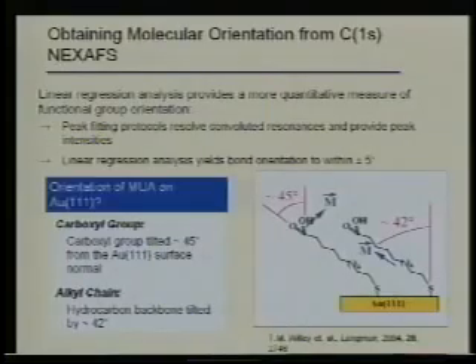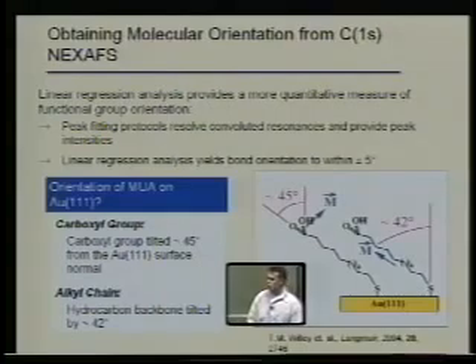So what these things actually look like, they're sitting on the surface, and the self-assembled monolayers are at 42 degrees from the surface normal. And depending, if you actually create it with an acetic acid, these things are standing up. If you create them in ethanol, they actually sit flat. So this, again, is like making hydrophilic, hydrophobic surfaces. And this is really great. This is a really powerful technique showing what molecules attach to surfaces and how you can actually feed back to the synthetic protocol and change things in real time.